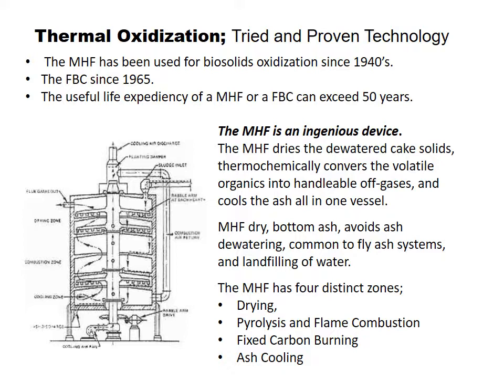The multiple hearth is a very ingenious device. What happens in a multiple hearth is the cake is introduced to the top of the furnace. It dries on the upper hearth, combusts in the middle, and you have carbon burnout and ash cooling in the lower hearth. It does all of this in one vessel. We talk about high performance digestion, oftentimes with multiple steps to do this. This unit does it all in one vessel. Also, the ash from a multiple hearth versus a fluidized bed is bottom ash, so it's dry. In a fly ash system, you have to wet the ash as it comes out of the top of the furnace. One guy told me, Stan, I don't want to dewater twice. I dewater my sludge once, I don't want to dewater the ash. So the multiple hearth has that advantage also.